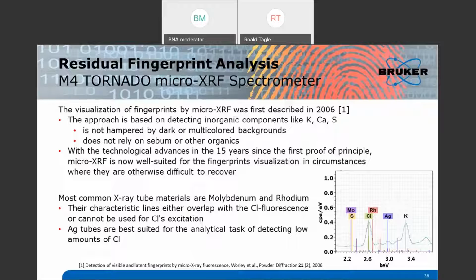And with this, we really try to visualize these residual fingerprints. So most common X-ray tubes usually, also there used to be the molybdenum tubes. Nowadays, rhodium is more common, but neither of them is perfect for this kind of analysis, as we will be showing, because especially the chlorine is a problem here. The overlap of rhodium with chlorine is significant, and this sometimes makes it difficult to detect low amounts.